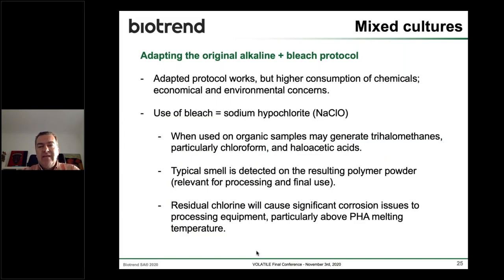And the state-of-the-art protocol, not using solvents, involves an alkaline treatment followed by a bleach protocol. The problem is that when we started to generate larger amounts of PHA purified using this process, the final users were complaining of a swimming pool smell of the polymer. And when the polymer was used to produce pellets that were to be extruded later on, so heated up and molten, they definitely detected a very strong chlorine smell,